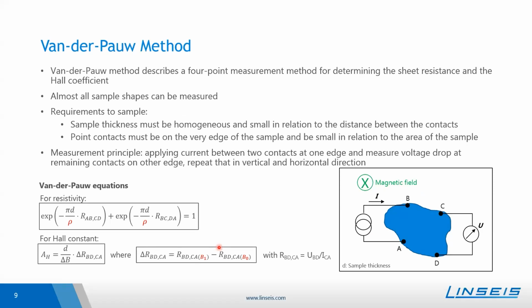In general, the Van der Pauw method describes a 4-point measurement method for determining the sheet resistance and the Hall coefficient. Advantages of this method is that almost every sample shape can be measured. So if the sample is round, rectangular, square, or clover leaf, or something irregular shaped, like indicated here in the sketch, everything can be measured. But there are two main requirements to the sample. On the one hand, the sample thickness must be homogeneous and small in relation to the distance between the contacts. The 4 contacts, ideally point contacts, must be additionally on the very edge of the sample, and the contact area must be small in relation to the area of the sample. So these are the main requirements so that this Van der Pauw measurement method works.